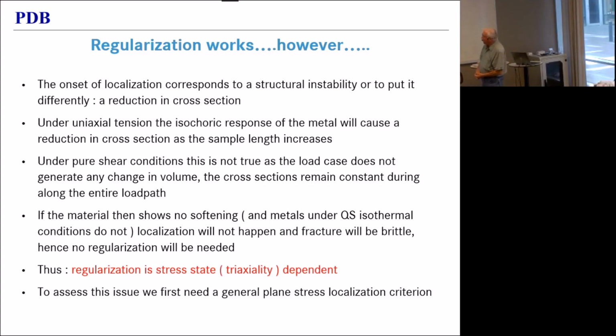Under pure shear conditions, we will not generate any change in volume. We will not generate any change in cross-section. And if the material has no softening, and metals under quasi-static isothermal conditions do not have any softening, then there will be no localization. And to regularize your failure model will be extremely misleading. In other words, regularization is stress state or triaxiality dependent. And there is a dramatic example of that in the next slide.